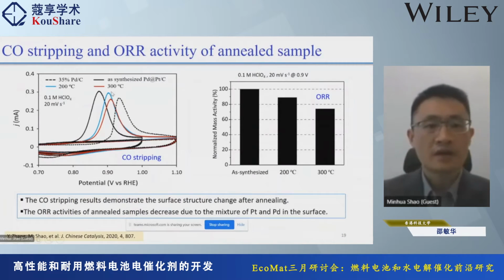Okay, and we also use the CO stripping to confirm this kind of structure change, right? So the black line is a synthesized core shell, and the dashed line is basically on pure palladium. So you can see that as a synthesized core shell catalyst, the CO stripping peak is actually much lower than the pure palladium. But after the heat treatment, it is actually shifted closer to the palladium.